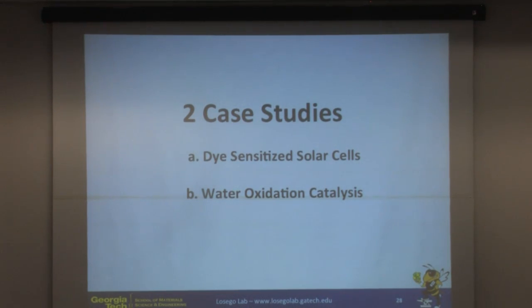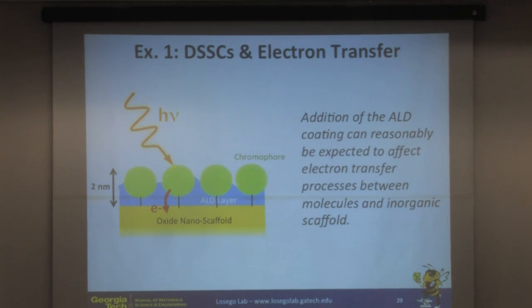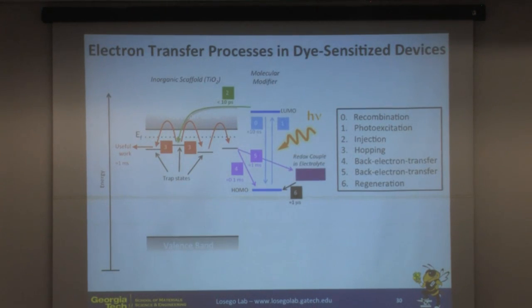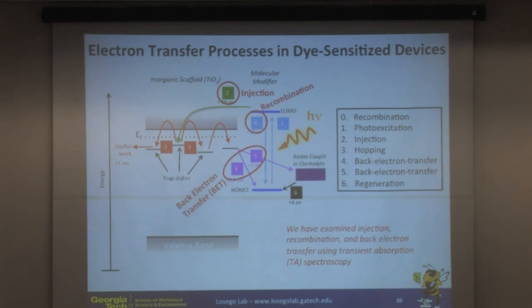So the first example are for dye-sensitized solar cells. And so we might imagine that if we start applying an ALD layer to a dye-sensitized solar cell, that it may act or may somehow manipulate the transfer of electrons that needs to occur from the dye molecule into the nanoscaffold. Okay, so this is what we would expect to occur, and it is what we observe. So this is just, again, a band energy diagram of all the processes that are occurring. And we can look at some of these processes using transient absorption spectroscopy, right? So we look at the rate at which each of these processes occur.